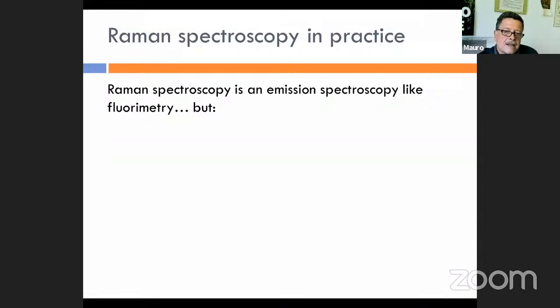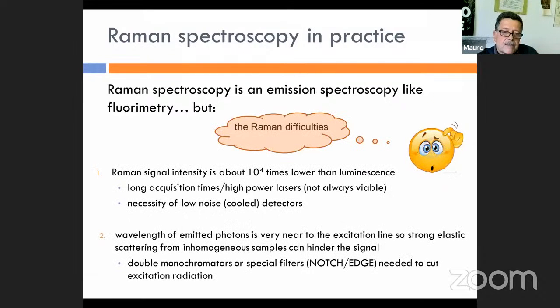What are the other characteristics of Raman spectroscopy which in the end affect its experimental feasibility? Well, Raman has some difficulties because the signal intensity is very low. The typical signal intensity of the Raman effect is 10 to the 4 times lower than luminescence. So to measure good quality spectra, we need long acquisition times or high power lasers, which is not always possible because a high power laser can heat the sample or damage it. Also, we need very good quality detectors or cooled detectors to reduce the noise associated with the measurements.